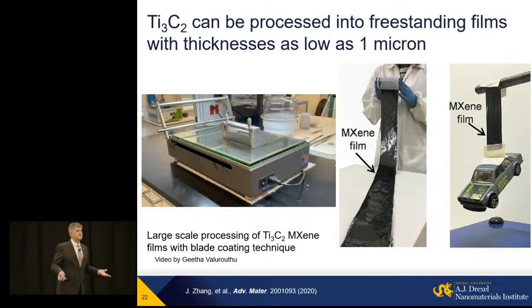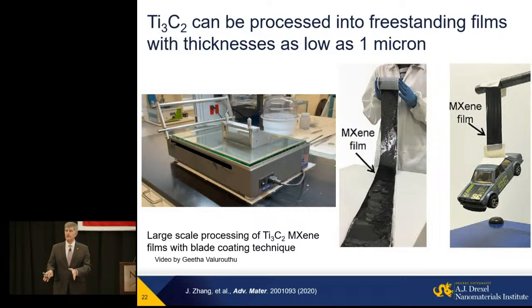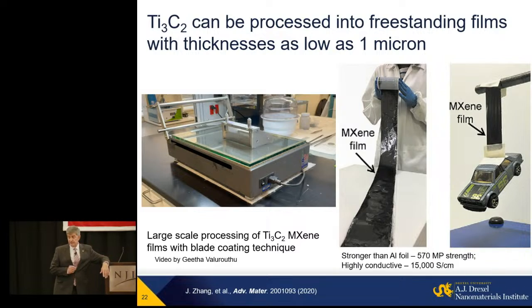So what do we do with these materials? We get a variety of properties. We typically process them simply from solution in water, but you can disperse them in polar organic solvents, or modify the surface by organic molecules and then disperse them, or chlorine-terminated MXene in non-polar solvents as well. And making films is very easy.